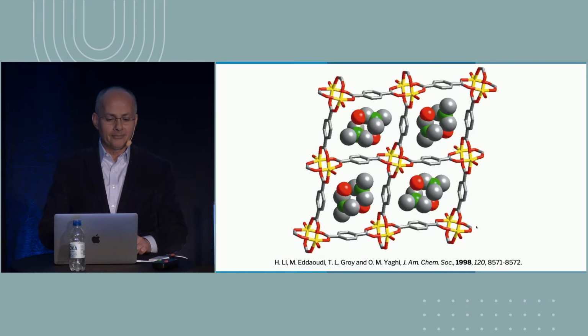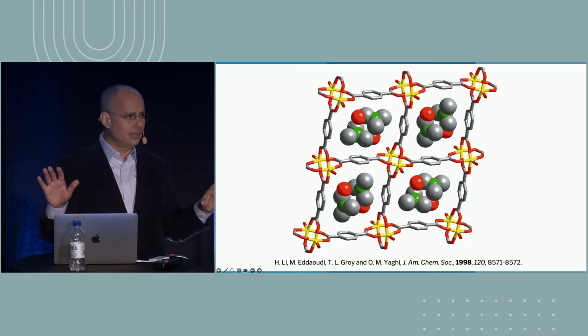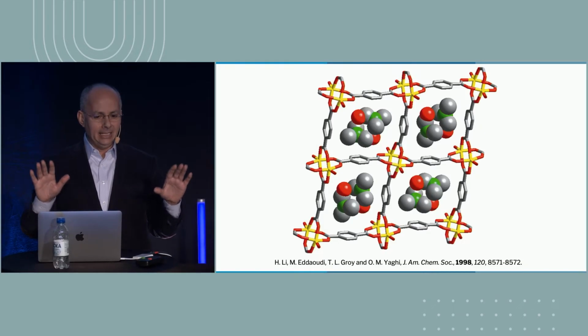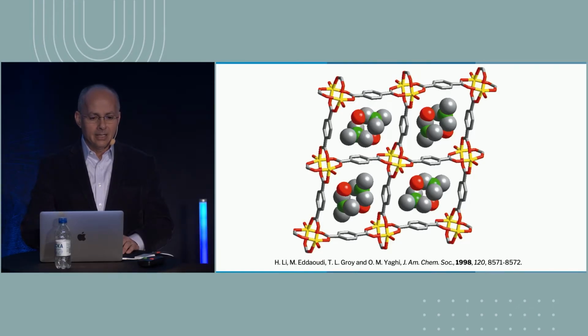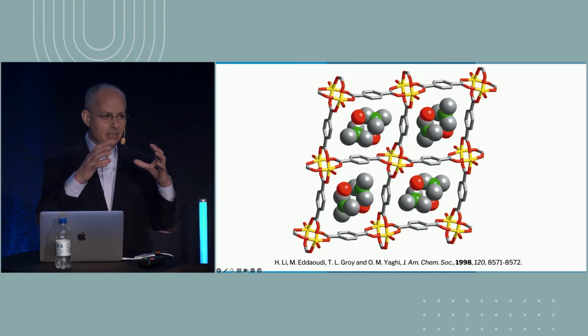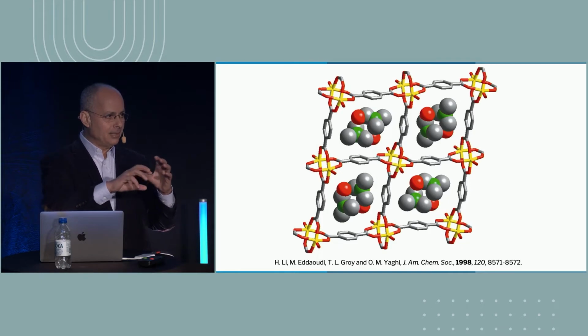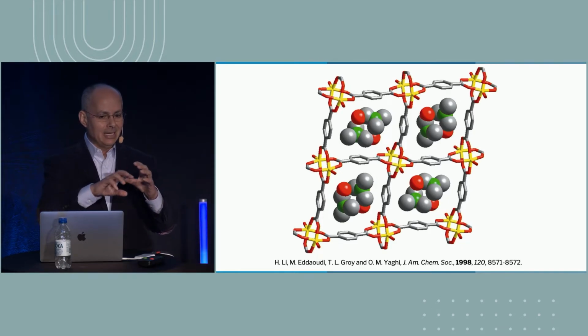And what did we make? We made this structure, which is exactly what I described before, the cluster that I described before, linked infinitely to make a two-dimensional grid. And because terephthalate is a long linker, and this cluster is large, now you have space into which those solvent molecules that were present during the reaction are trapped.